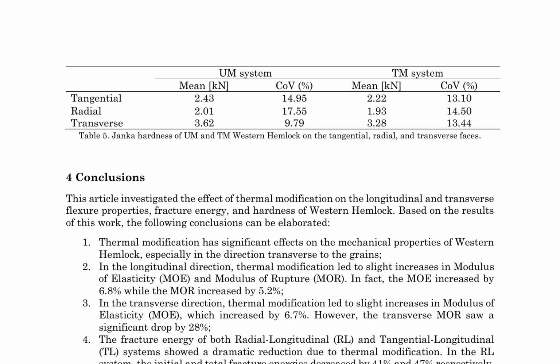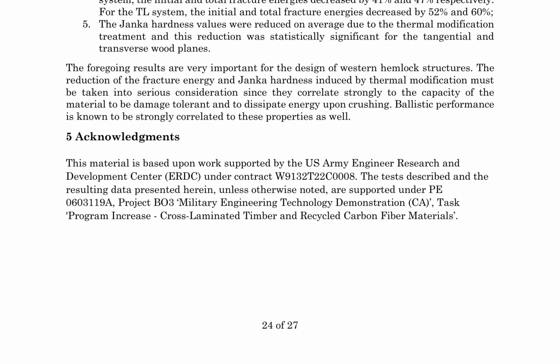Janka hardness tests revealed that average hardness values were reduced due to thermal modification, with a statistically significant decrease observed in the tangential and transverse wood planes. This decrease in surface hardness is consistent with previous research, which showed that surface hardness generally decreases with thermal modification, especially at higher temperatures. The results of this study underscore the importance of considering the effects of thermal modification on Western hemlock's mechanical properties, particularly in terms of its potential use in structural applications.